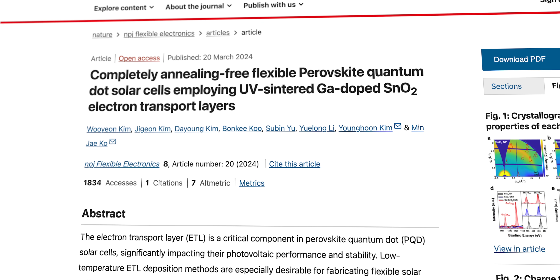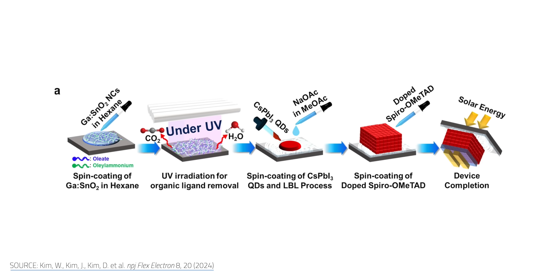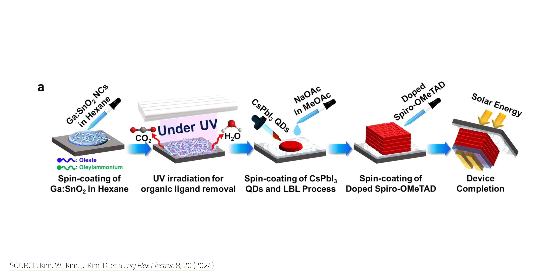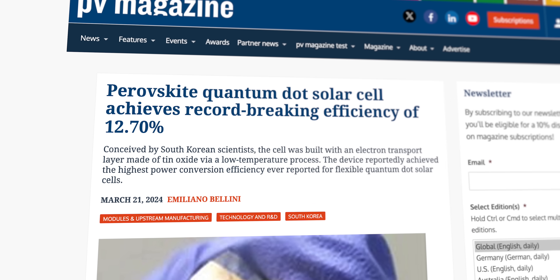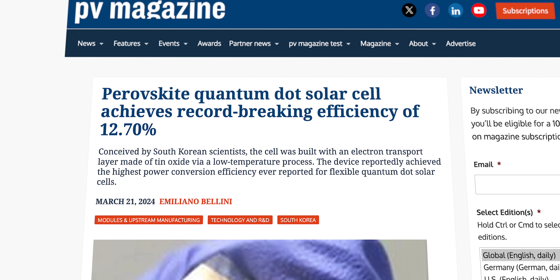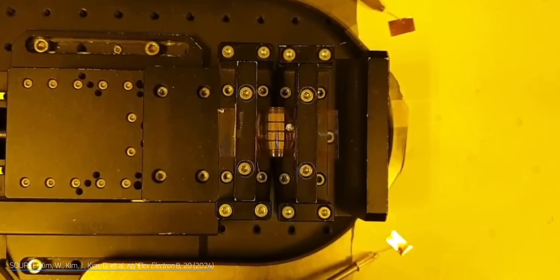Meanwhile, a totally different team of scientists from several Korean universities and institutions developed a flexible quantum dot solar cell based on all-inorganic cesium lead iodide — or black perovskite. They can deposit a coat of these perovskite quantum dots quickly and at room temperature using a simple layer-by-layer process to create a flexible cell. The room temperature approach is very important since quantum dots don't like too much heat. Ordinarily it takes heat treatment to connect perovskite quantum dots to the base layer, which increases the risk of defects. Being able to do this at room temperature takes a lot of the headache out of manufacturing. The team reported power conversion efficiency of 12.7% under standard testing conditions — a new record for flexible quantum dot PV, and all from just the last few months of 2024.